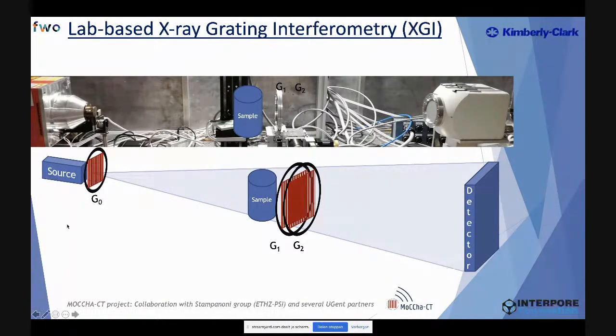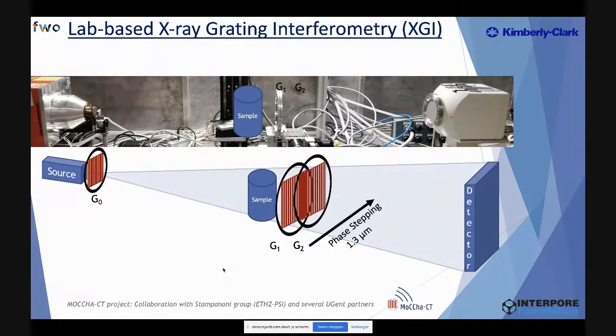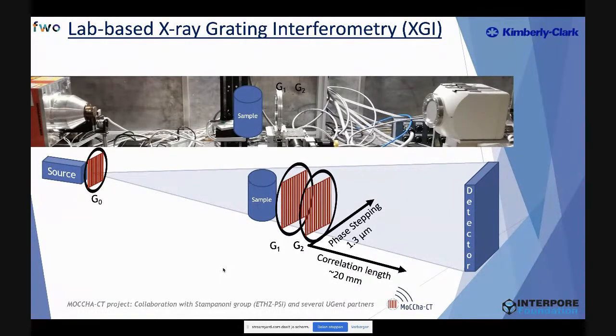Here you have a lab-based system where you also have your source, your sample, and your detector, similar to normal CT, but then you put the gratings in between. You can position these gratings parallel to each other and away from each other, and by doing so, the intensity in the pixels changes while changing the positions of those gratings, and this allows you to obtain the dark field signal.